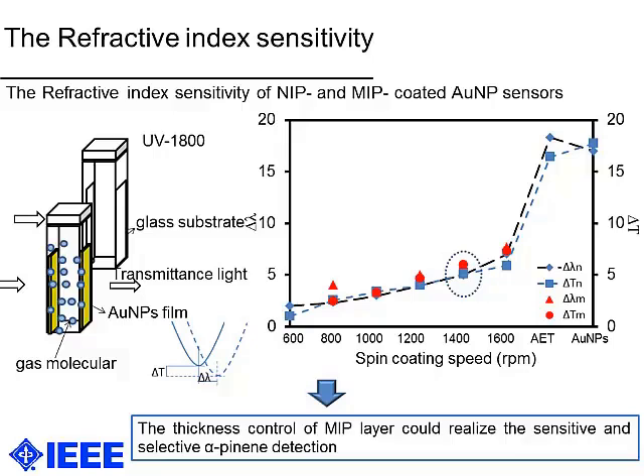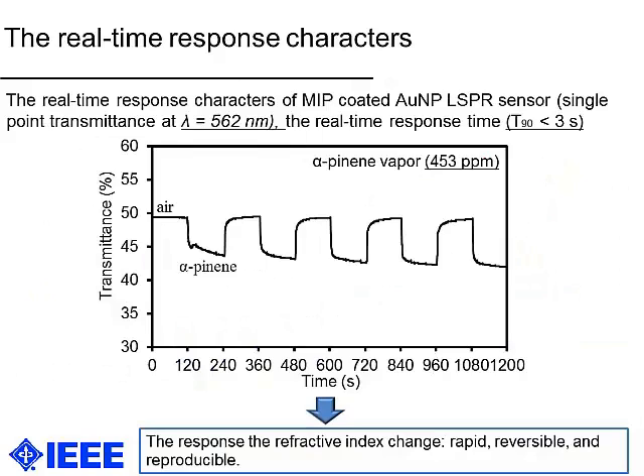And the result is shown like here. Here, when the spin coating speed is nearly 1,400, the NIP and MIP results are better separated, and the sensitivity of MIP is better than NIP. So here we think that this is the optimum spin coating speed. From this result, we conclude that thickness control of the MIP layer could realize sensitive and selective alpha-pinene detection. And also we detected the real-time response characteristics of this MIP-coated Au nanoparticle substrate.